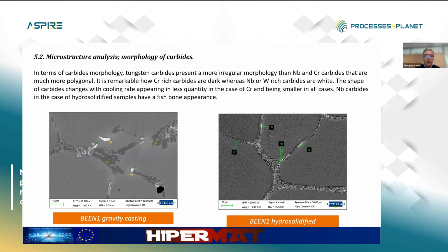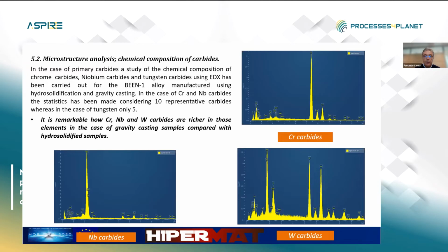Well, if we take a look at the morphology, in the case of the standard samples cooled down in the mold, we can see these blocky type carbides in grain boundaries, whereas the shape of carbides changed completely in the hydrosolidified samples. It looks like a fishbone appearance. They are tiny, and they are better distributed. This is quite significant.